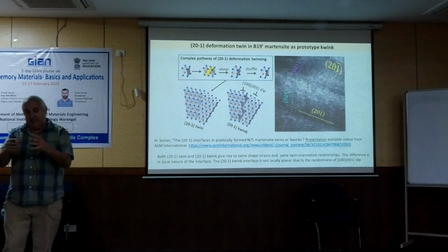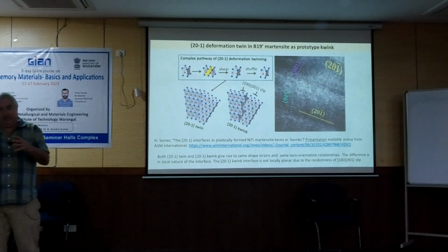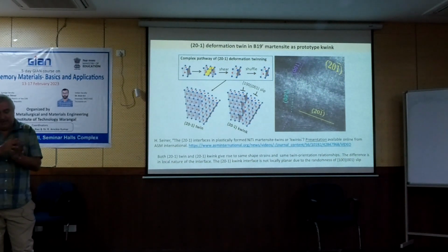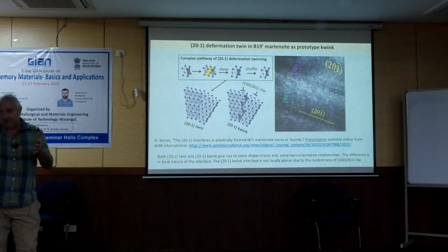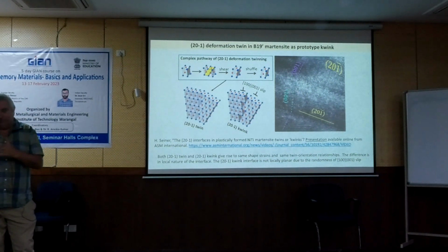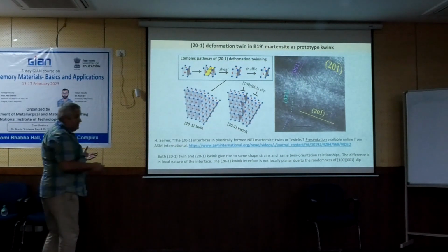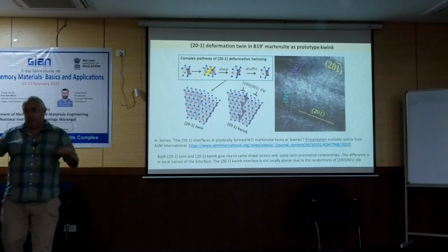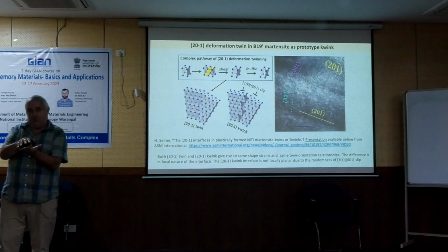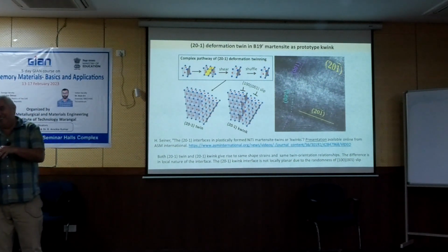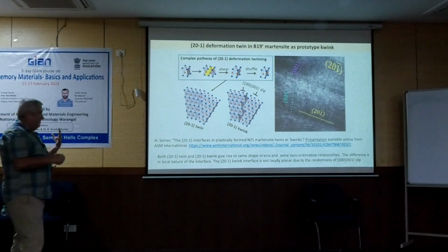That's why in materials like magnesium, you always have deformation twinning and dislocation slip together. You have deformation twinning and the lattice around is deformed by slip. The same with TRIP in the steels: you have transformation and slip as well. In our case, it is different. We don't have slip as well because the material is so anisotropic, like this stack of sheets. But we have the slip inside the band.